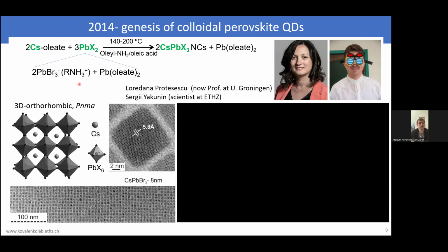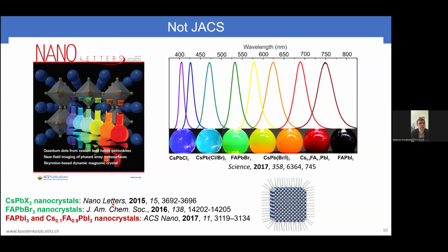And why is this reaction that fast? Because your precursor is already ionized because of the mixture of these long chain acids and amines. You have long chain ammonium, which stabilizes your bromoplumbate, and therefore you already have a lot of these species to co-precipitate with cesium. Nevertheless, despite this sort of fast ionic co-precipitation, we did get reasonably monodispersed quantum dots. And then we extended their compositions to mixed halides or to hybrid compositions, formamidinium, then methylammonium, and that became a very popular type of quantum dots to sort of replace cadmium-based ones.